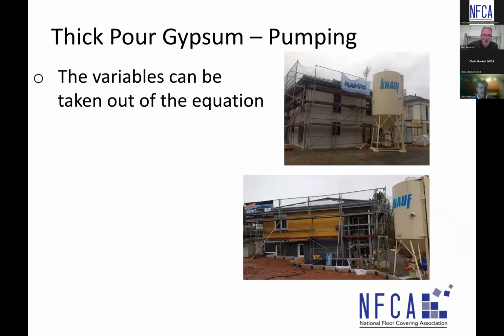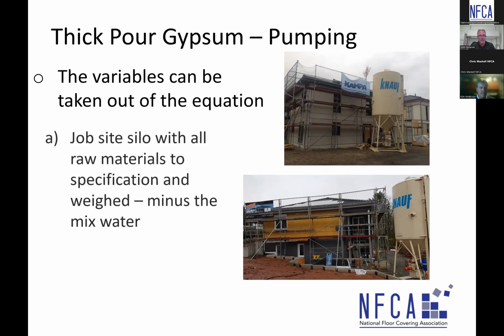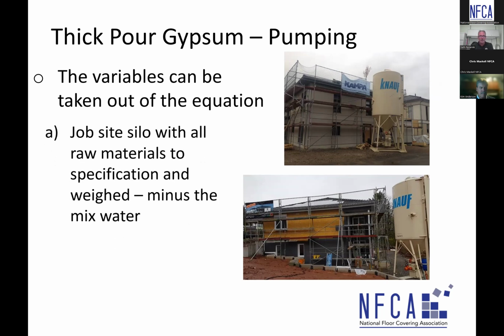So that's one way to take variables out. Another way that we can take variables out of the equation is an on-site silo with raw materials that are weighed out to very specific weights, so that it's the right ratios, the right amount of gypsum and the right amount of sand. Then that silo of the properly blended sand and gypsum is placed into a hopper where the water is added and then mixed and taken to the site. That's another option to take variables out of the equation.